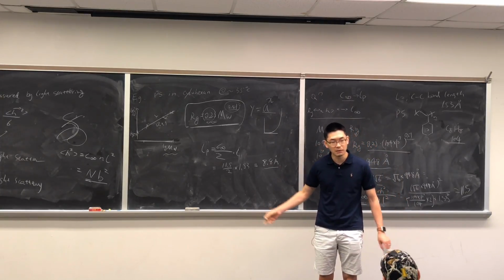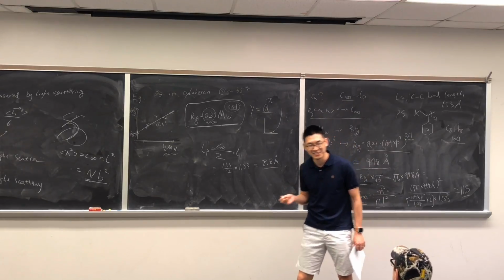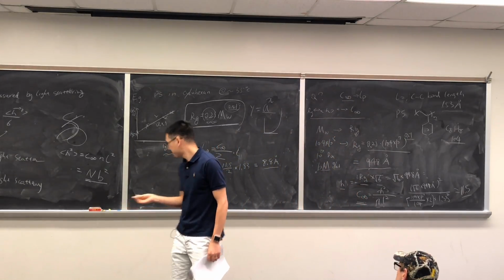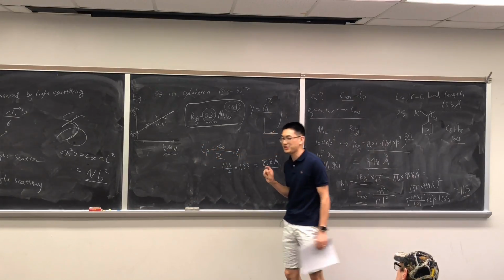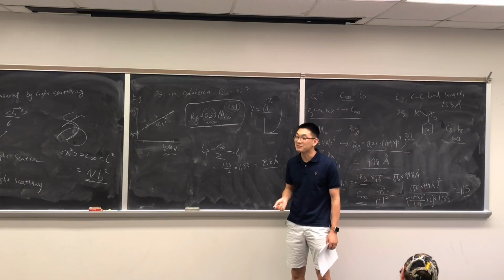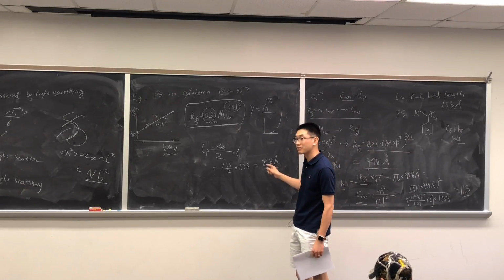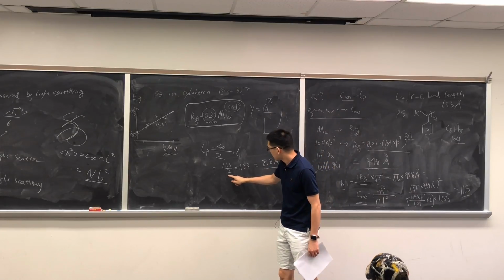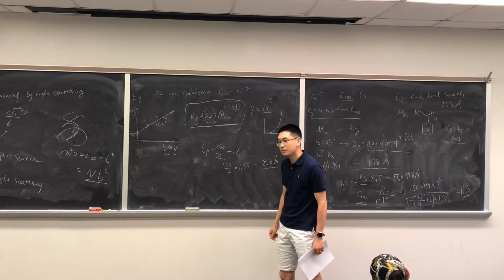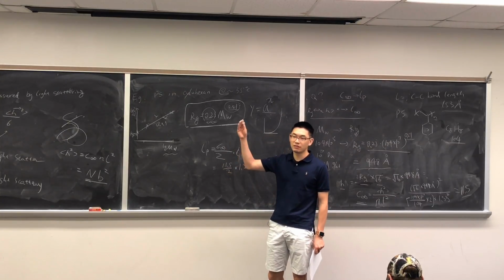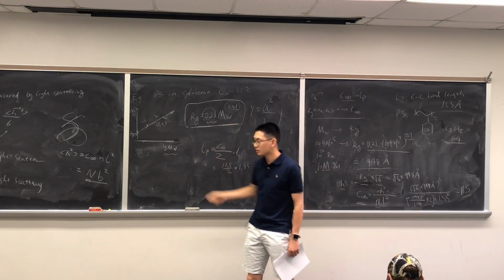So the physical meaning we discussed in the class. What does this mean? After about 8.8 angstrom, your chain could bend over 90 degrees. So your chain is relatively short-ranged, and this is just above 6 bonds, a little bit less than 7. Your chain can fold back to 90 degrees.